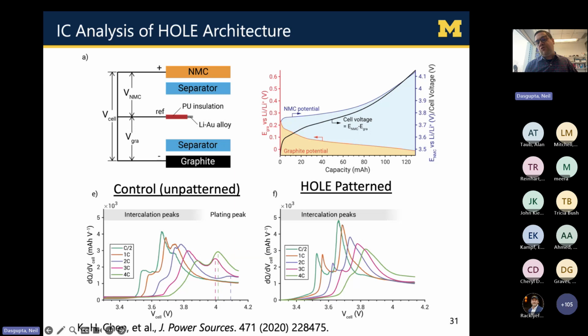derivative of this. So we do incremental capacity analysis. This is something that is used a lot in battery diagnostics, battery controls analysis. We can see here that in the control unpatterned cell, we see a lot of changes in this dQ/dV spectrum. Again, I don't have time to go into all the details here, but I can point you toward this paper we published in the Journal of Power Sources that really breaks down the interpretation of the dQ/dV spectrum for batteries under fast charge conditions using 3-electrode measurements. And what we see is with the hole patterned cell, we don't see the evidence of this peak that occurs associated with lithium plating.